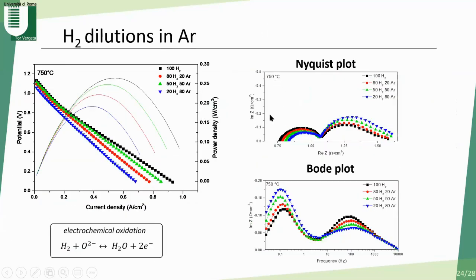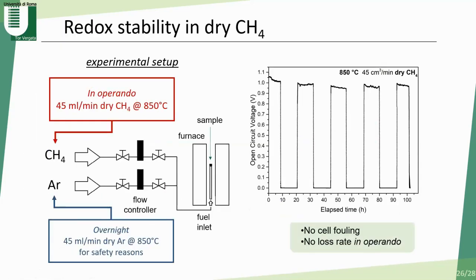From impedance measurements made at different dilutions of hydrogen, we can see that of the two semicircles observed from the Nyquist plot measured at OCV, the first semicircle, at lower frequency, is mainly due to the anode, while the higher frequency semicircle is mainly related to the cathodic reaction, even though this difference can be further investigated. Then we switched and we tested the same cells in presence of dry methane at 850 degrees C.